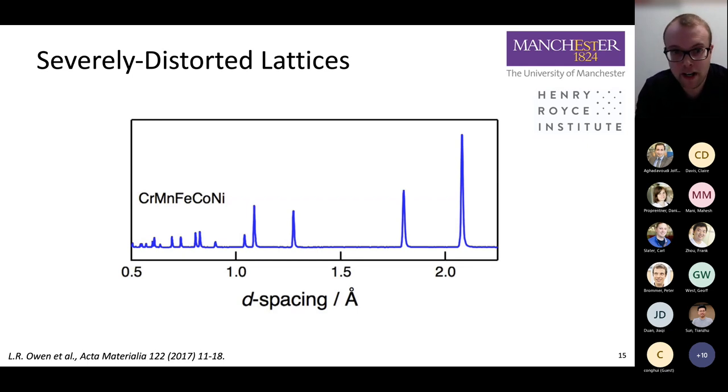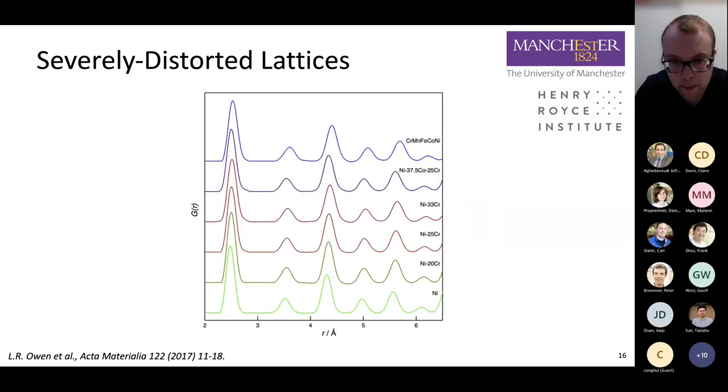They do neutron diffraction measurements, total scattering measurements like this, Fourier transform that, and then they generate pair distribution functions that can then be compared with various models. And you can see here that if we compare the widths of these peaks, you might be able to convince yourself, okay, that the high entropy alloy does have a greater peak width here.